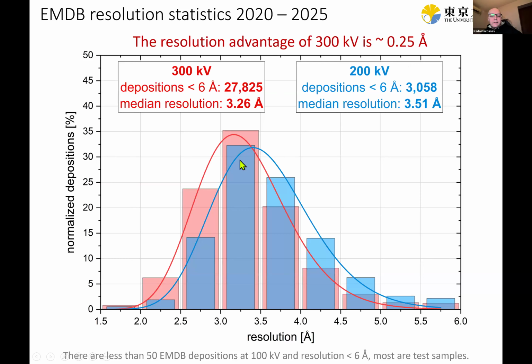So the devil here is also in the detail, and if you look at the high resolution region below 3 angstrom, then we see that the discrepancy is getting bigger. So for example, the region between 2.5 and 3 angstrom, the 300 kV is about 2 times more prolific, relatively speaking, because these are normalized histograms. And then in the region below 2.5 angstrom, it's 3 times more prolific than the 200 kV. So in these regions is where we get good quality maps that help us get higher fidelity models, better modeling of side chains, also small molecules, if we have some kind of a ligand, and water molecules, which are becoming more important for evaluating and investigating the function of proteins.